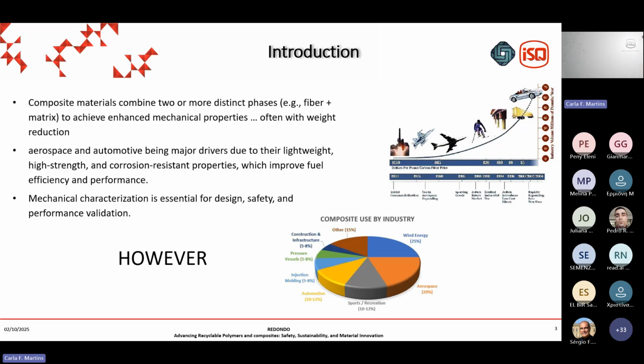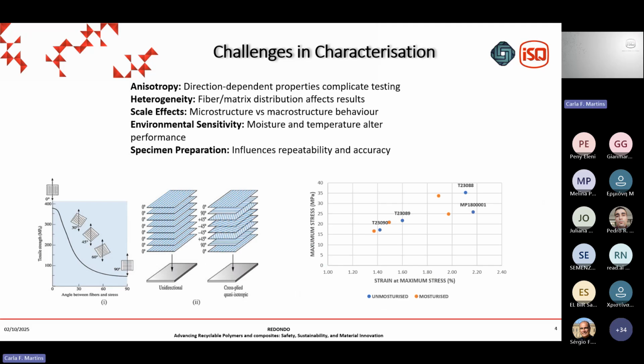By the way, I am a bit focused also on polymeric-based composites. There are other forms of composites, but when I mention composites, I'm referring to these polymeric materials. So, as I said, one of the major problems in these characterizations is the anisotropy or the potential anisotropy of properties compared with traditional metal alloys, which are mostly isotropic. So usually we can do some limited number of tests and they are valid for the bulk of our material. With composites that might not be true. It could be true in some composites reinforced with short particles or fibers, but not with longer fibers and fiber orientation.